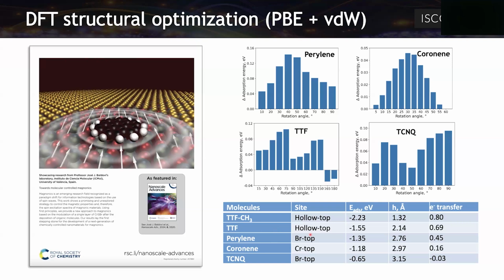Regarding the energies, all of them are negative, so they are possible, they are stable on this surface. We were testing TTF, perylene, coronene, and TCNQ, but the best result we got was for TTF, which has this adsorption energy of minus 1.55 electron volts. It is closer, at 2.1 angstrom to the surface, and we have this 0.7 electron transfer. We wanted to increase the donor character of this molecule, because the more donor the better in this case. And we add a methyl group here in the TTF. We substitute the hydrogens, and we observe a better adsorption energy. The molecule got closer and more electron transfer. So we have a good candidate now to control the properties in the chromium sulfur bromide by molecule.